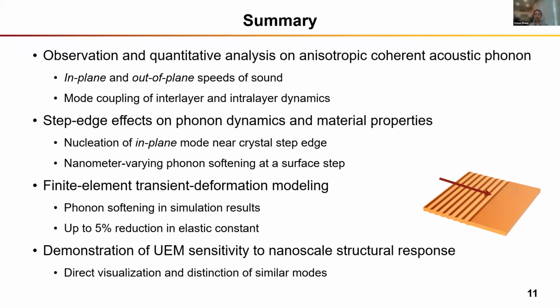So in summary, we observed and quantified anisotropic coherent acoustic phonon, both in plane and in the z direction. We observed a mode coupling between the two different modes of the phonon. We also found the step edge plays a key role in the overall dynamics, including serving as the nucleation site for in-plane mode and leading to nanometer varying phonon softening. And such effect can cause up to 5% of reduction in the elastic constant.